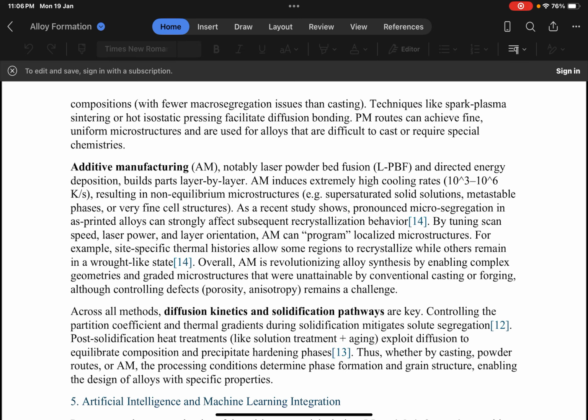The next one is additive manufacturing. Additive manufacturing uses extremely rapid cooling, creating non-equilibrium microstructures. Additive manufacturing, notably laser powder bed fusion, LPBF, and directed energy deposition, builds parts layer by layer. Additive manufacturing induces extremely high cooling rates, 10^3 to 10^6 kelvin per second, resulting